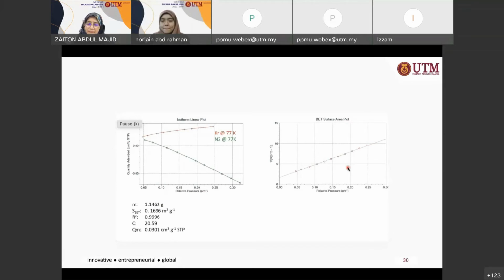So the point here is that the first thing that you need to see is that the amount of uptake must increase with increase in pressure. If you have it decreasing, then something is wrong. Check for leaks, check for sample, check for the temperature and so on, the degassing, sample preparation. Okay. And then when that is okay, then run the BET surface area transformation plot. If you get a negative C, then something is also wrong, which you need to check.